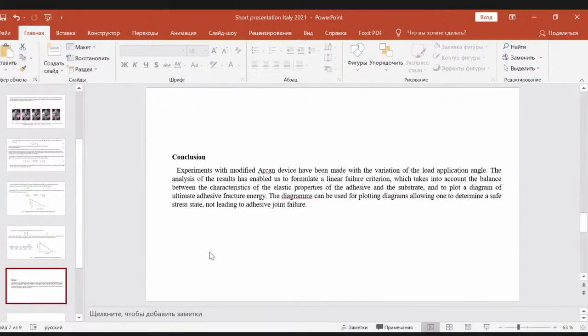Conclusion. Experiments with a modified Arcan device have been made with the variation of the load application angle. The analysis of the results has enabled us to formulate a linear failure criterion which takes into account the balance between the characteristics of the elastic properties of the adhesive and the substrate, and to plot a diagram of ultimate adhesive rupture energy. The diagrams can be used for plotting a diagram allowing us to determine a safe stress state, not leading to adhesive joint failure. Thank you.